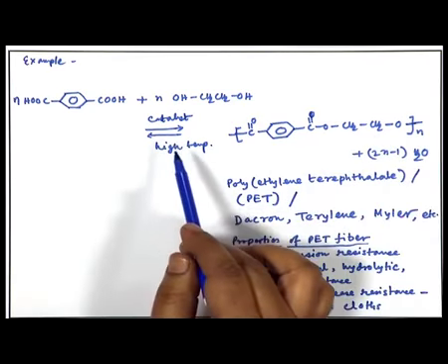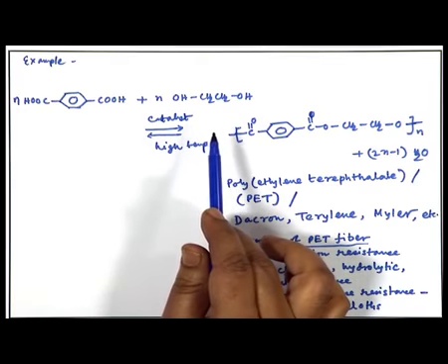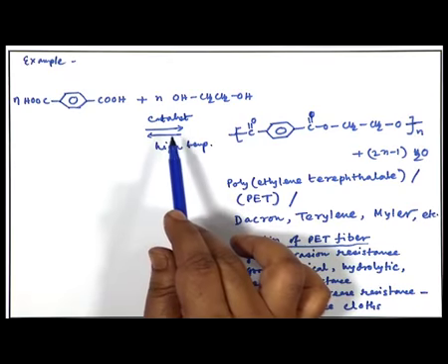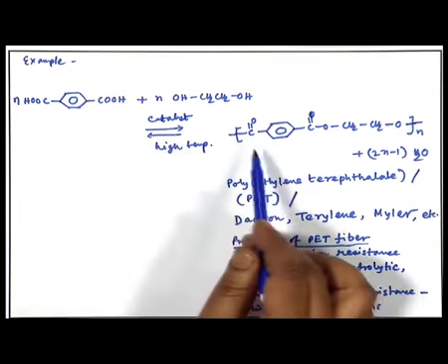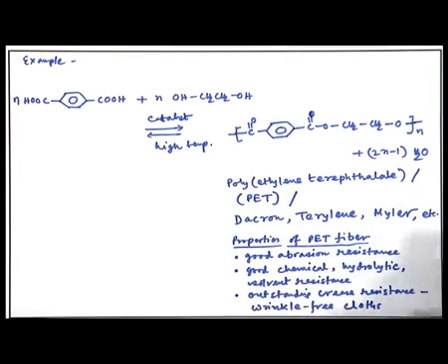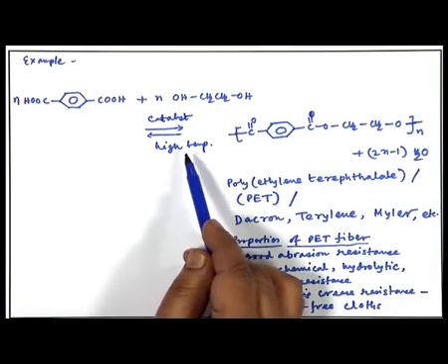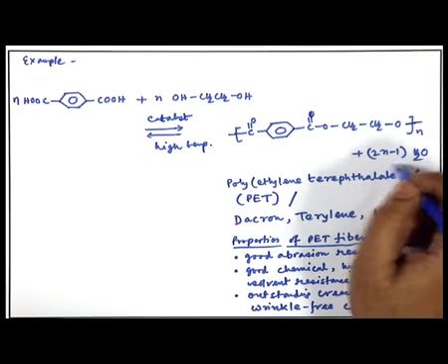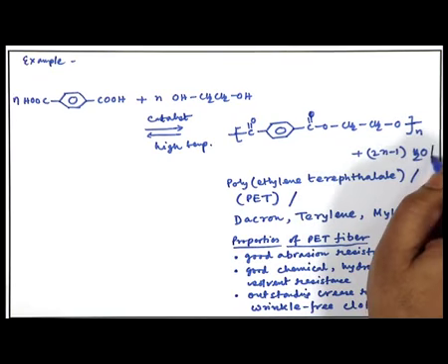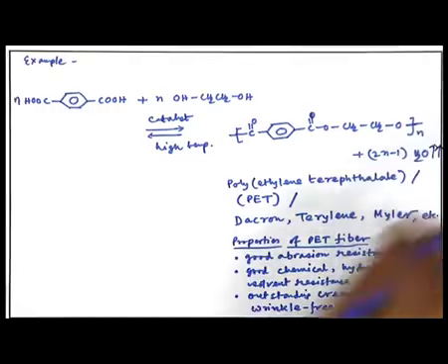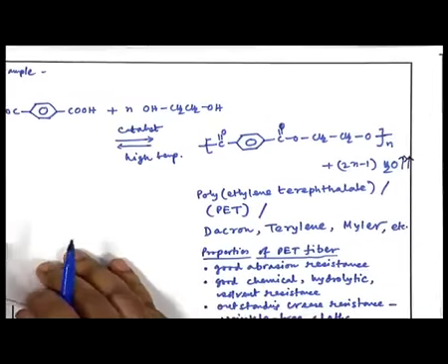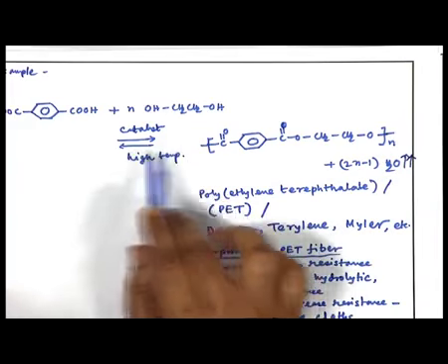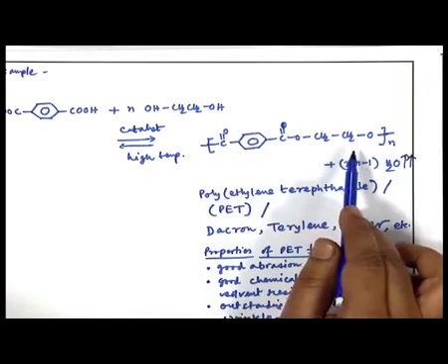Now, unlike the polyamides, this reaction is not a very fast or very feasible reaction, actually it is a reversible reaction. So, to get this polyester formed effectively, you have to increase the temperature so the reaction happens fast, and we also have to apply low pressure or vacuum and take the water out of the system, so that the equilibrium or the reversible reaction proceeds toward the product side.